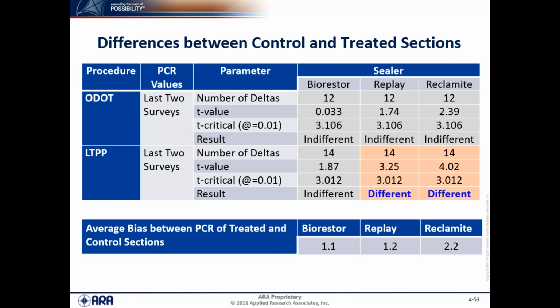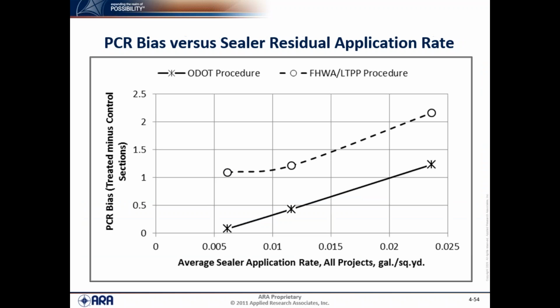For example, if the PCR for the control for the Bio-Restore test sections was 80 on the average, then the average for the treated Bio-Restore sections was 81.1. And conversely, for the Reclamite, if the average PCR for the control was 80, then the average PCR for the Reclamite was 82.2. So that's just an average bias between the two that we calculated.